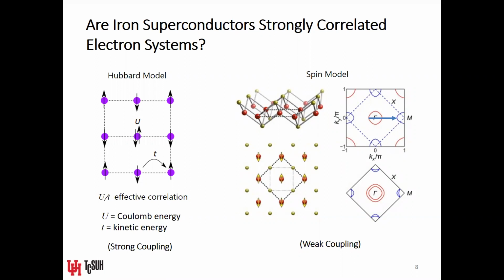Okay, for one thing, let me just say that it appears that the iron bands in these superconductors can actually have varying degrees of electron correlation. So the D bands in the iron superconductors, some of them may be more itinerant than others. Some of them may be more bound in terms of their ability to conduct compared to other D band states. But early on, this was a question, and at the heart of that question was whether or not the Hubbard model could actually be used to describe the physics of iron-based superconductors.